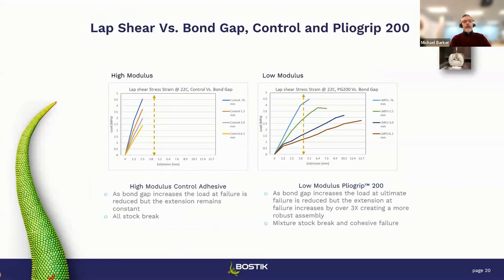So we took that a little bit further, and we took those same adhesives, the control on the left, and we varied the bond gap. So we were at 0.76, 1.53, and 6 millimeters. And as we tested them, you can see that they all failed at approximately the same extension. Now, the strength values differ, but as we increased the bond gap, the strength came down. But they all failed at the same extension. And why is that? Because they all broke the composite substrate. Now, over on the right, we did the same thing with the low modulus adhesive, and we started testing them. Now, we're varying the bond gap as previous, but now as the strength is coming down, the elongation is going up.